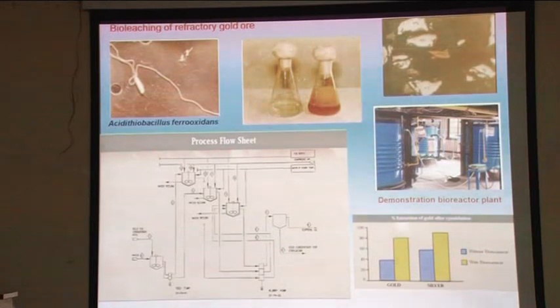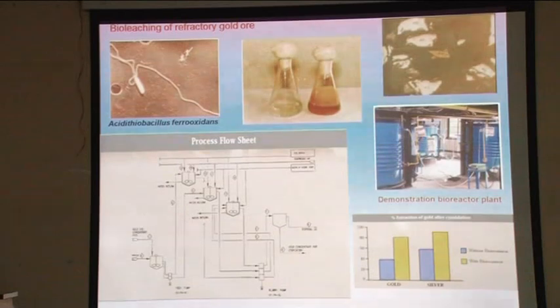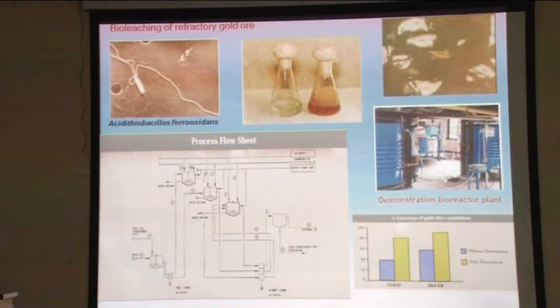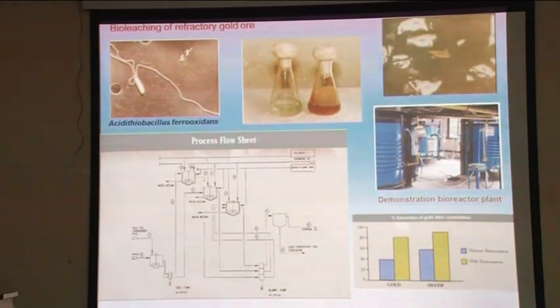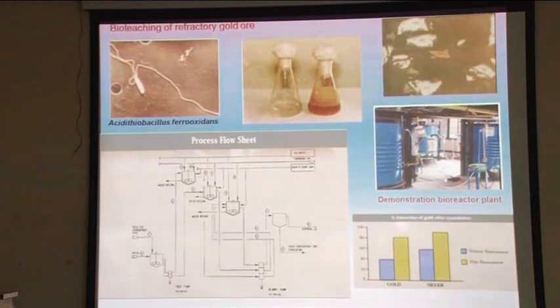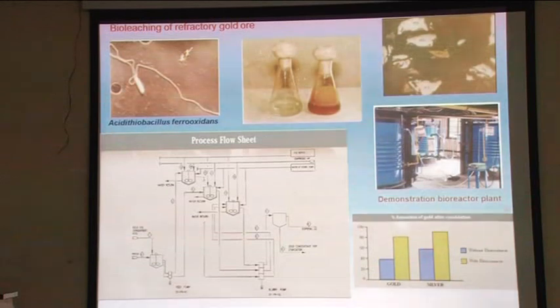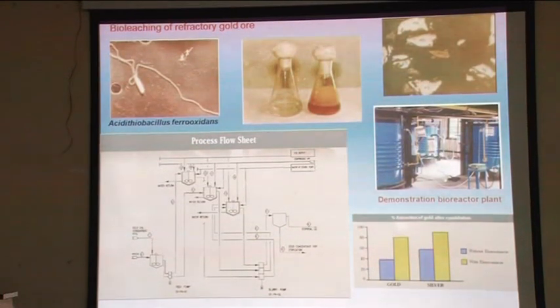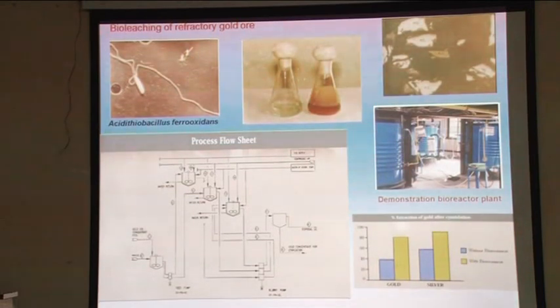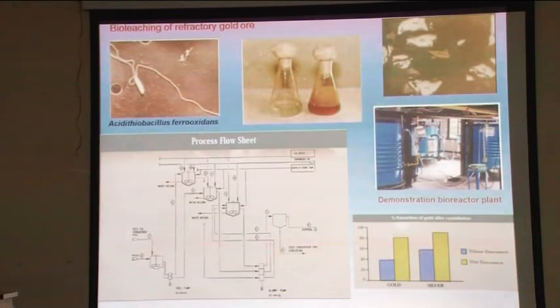And the first operations were over 100 years ago, started at Kolar gold fields. But the gold there is associated with the quartz, which is actually easy to extract. It's called a free milling gold ore. But we also have deposits of gold which occur within a sulfide matrix, that is pyrite and arsenopyrite. So that is the type of gold ore where you have to do a pre-oxidation step. And the bacterial leaching is done for this pre-oxidation. So basically it is not the gold that is dissolved, but the sulfide matrix is oxidized, and thereby the gold is getting liberated. So you will see here in this flask, this is the electron micrograph of the Acidithiobacillus ferrooxidans.